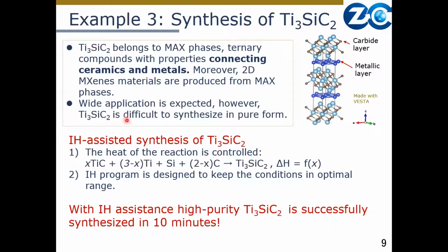However, this ternary carbide is quite difficult to synthesize in pure form. So we proposed our method for synthesis of titanium-3 silicon carbon 2. First, we control the heat of the reaction. This reaction is highly exothermic. So to control the heat, we add titanium carbide and then get optimal heat. And then we design an induction heating program to keep the conditions in optimal range. As a result, with induction heating assistance, high purity titanium-3 silicon carbon 2 powders were successfully synthesized.